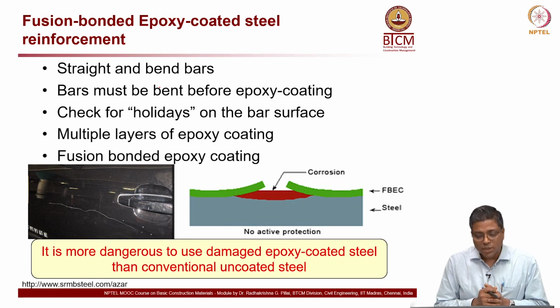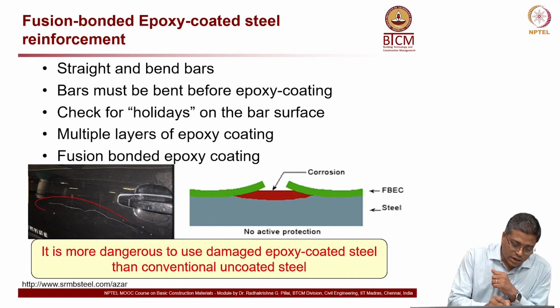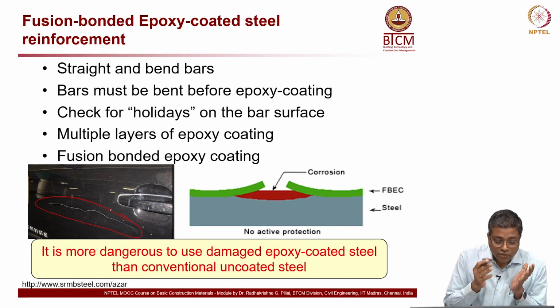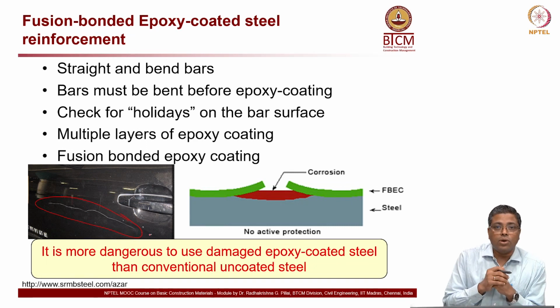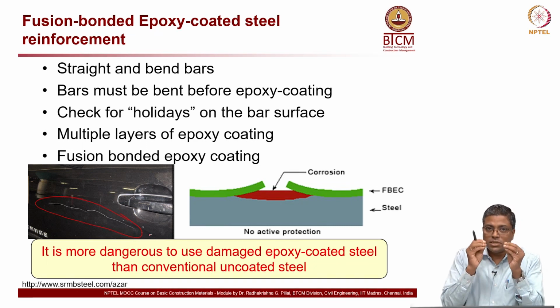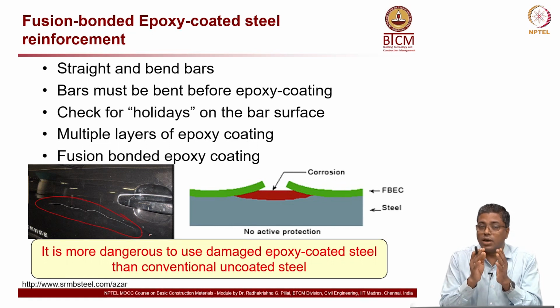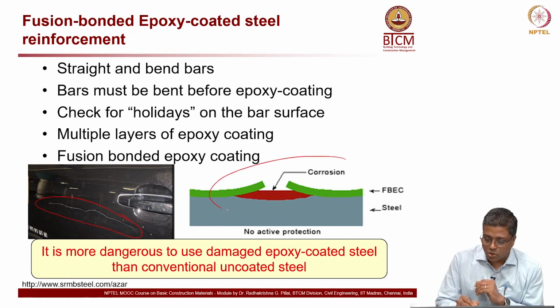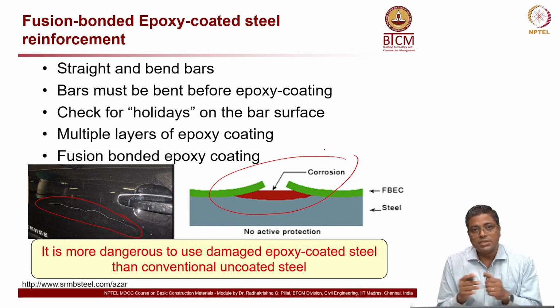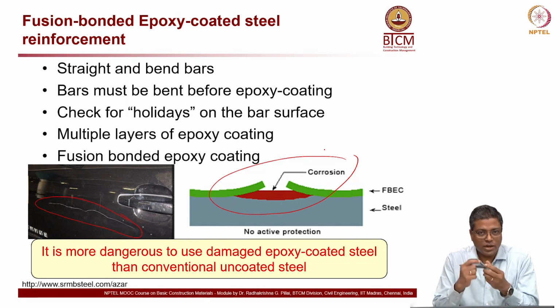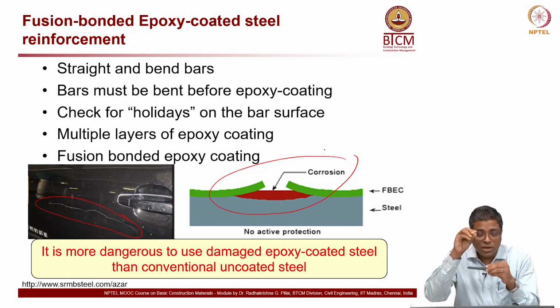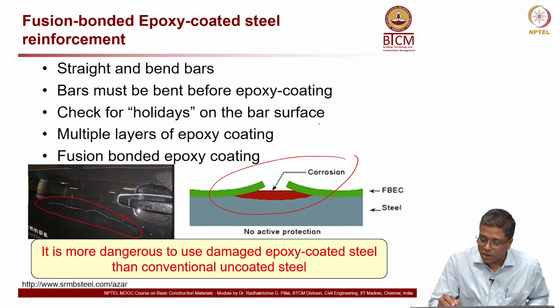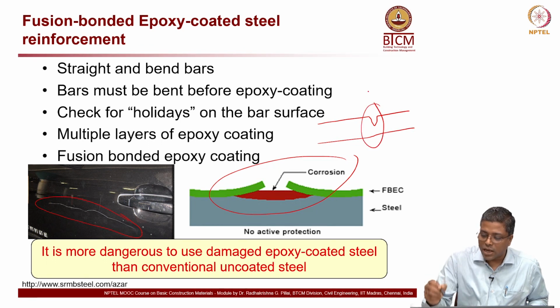Look at these two pictures, what is really happening. If you have a crack like this, what will happen? If it corrodes, it will corrode right at that crack alone, and the concentration will be high when you have localized corrosion. Similar to the picture shown on the right side, where the green is the epoxy coating and the red portion is the corrosion products, you have localized corrosion. The cross section of the rebar, the remaining area available, will be very significantly affected. So, if you have a rebar like this, it will corrode something like this. So, you have a localized corrosion attack.